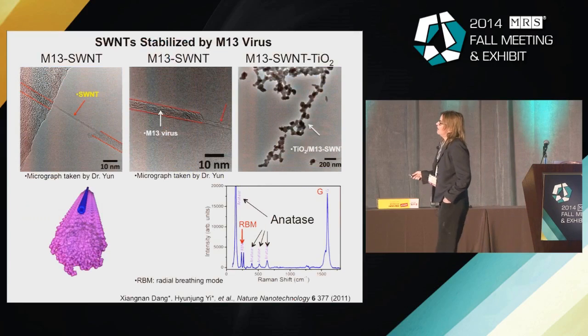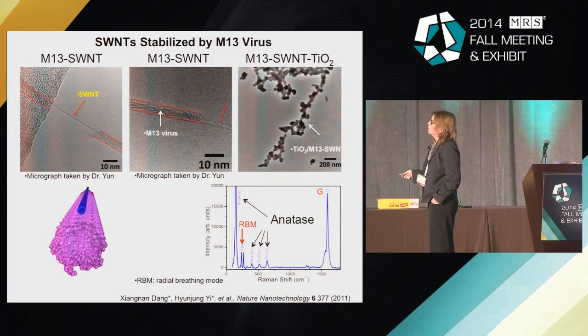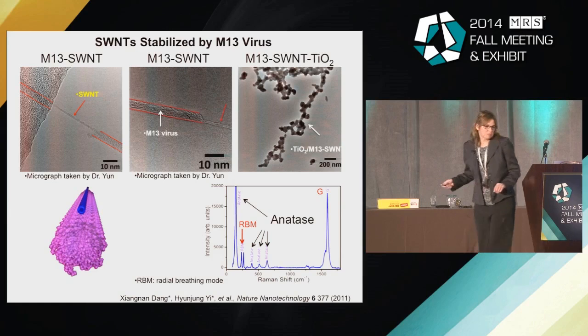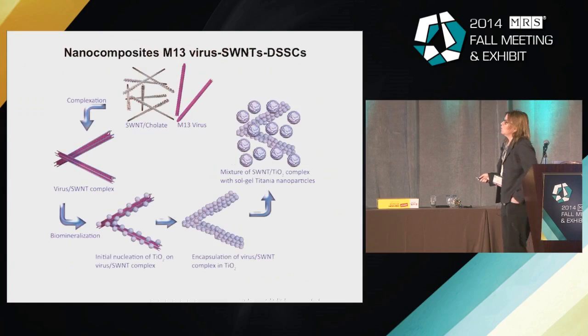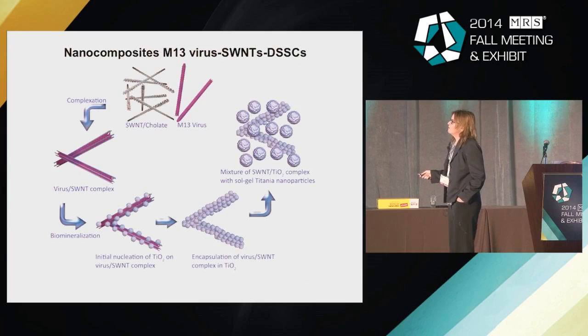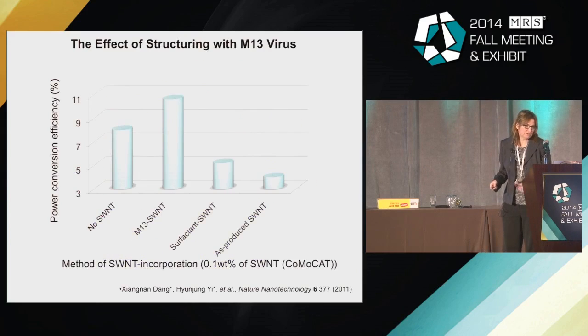So we had viruses that could pick up carbon nanotubes around their lengths, and then we could have a sequence that could nucleate titania out of solution. So now we had titania grown over our virus-based carbon nanotubes, and this was anatase. And so what we could do is now take our virus complex, grow the nanoparticles, and then put a small amount of these virus carbon nanotube titania complex into an already existing paste of titania and see how it would increase the efficiency of the solar cell, or if it would.